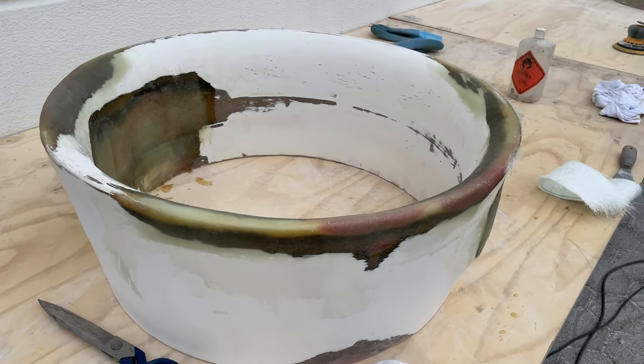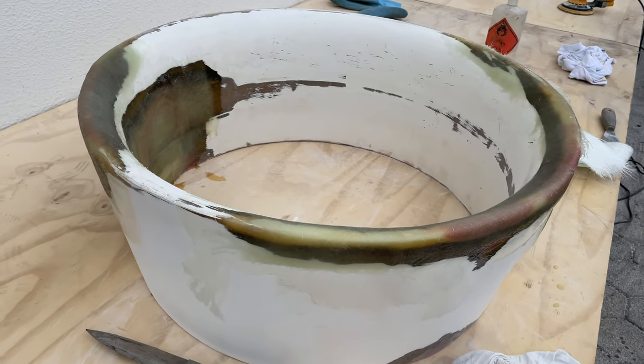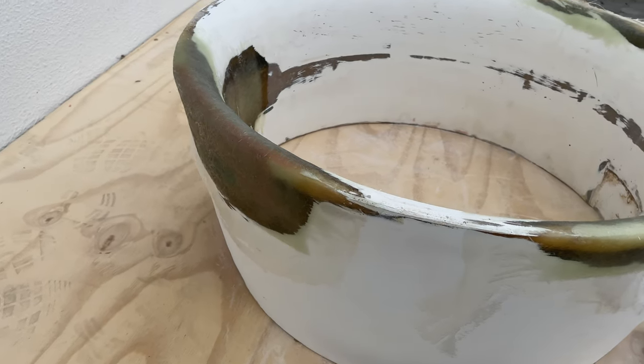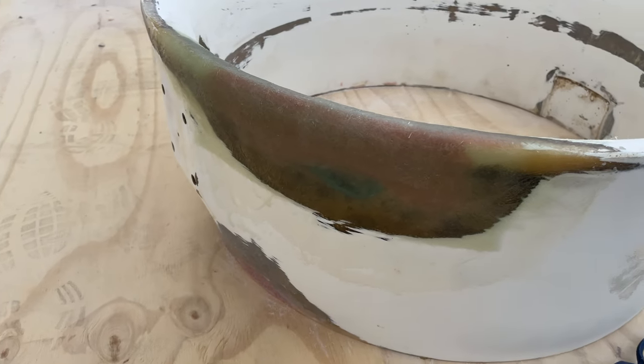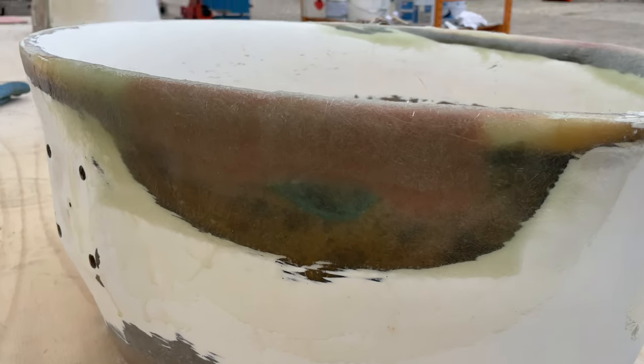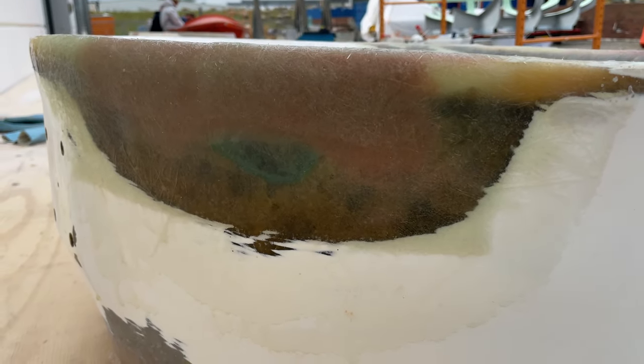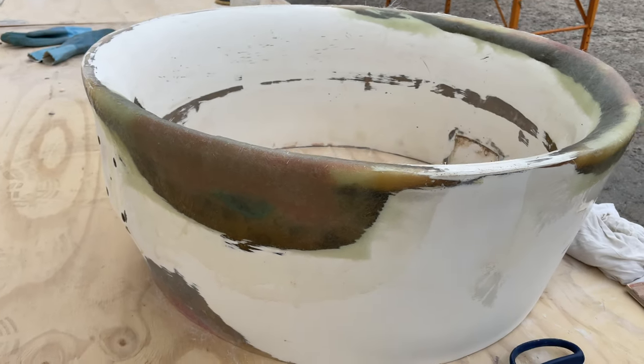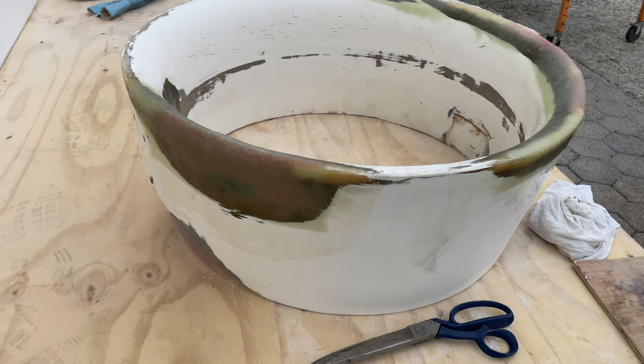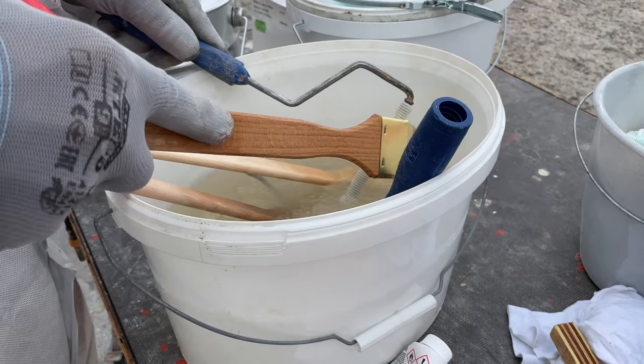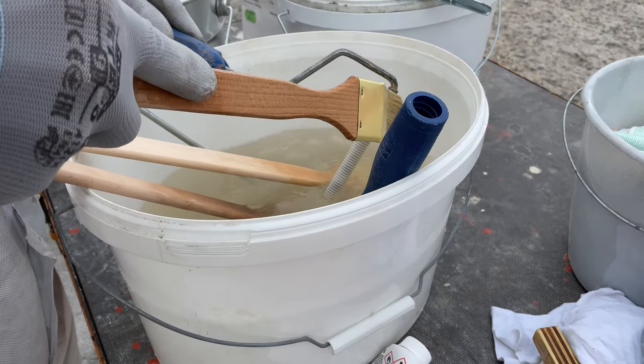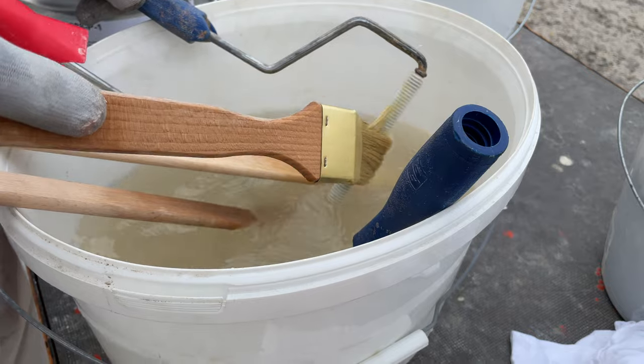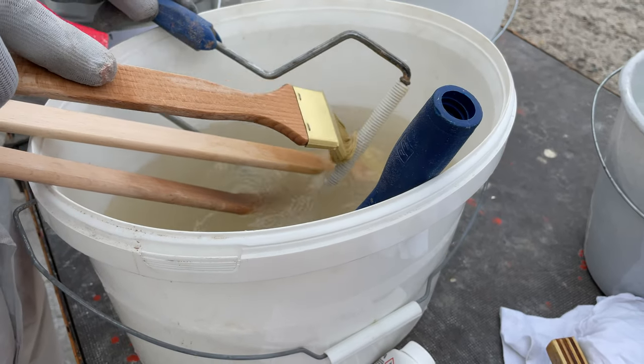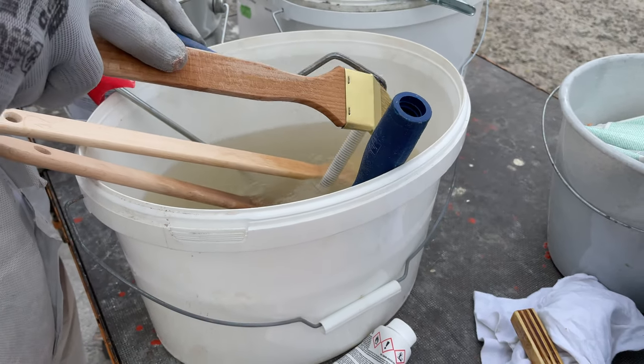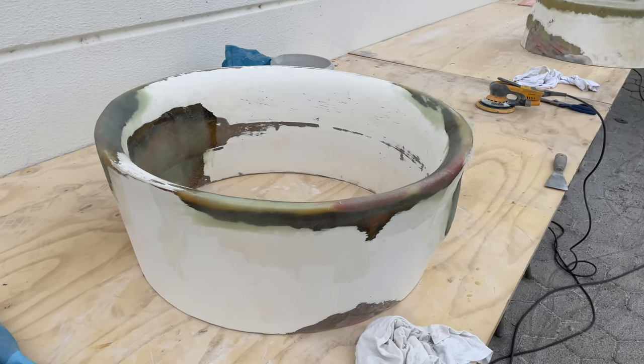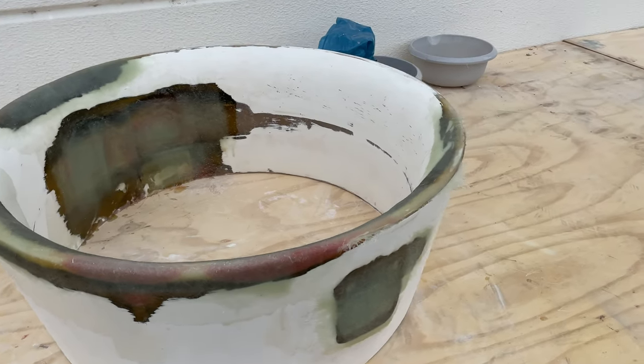If you see the material getting white where you've rolled, that means you've put on too much pressure. If you can still spot some air bubbles you can move around, then you have not put on enough pressure. Make sure to clean off your tools before the resin hardens. The shipyard uses acetone, but that's a very dangerous chemical. If you choose to go down that path, then please get yourself familiarized with all the safety precautions necessary.